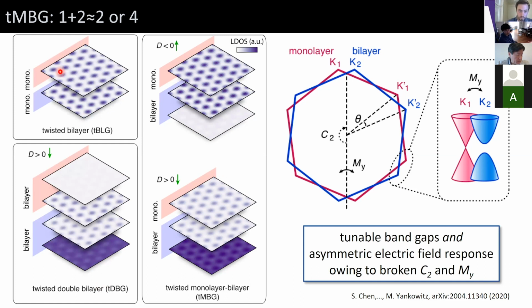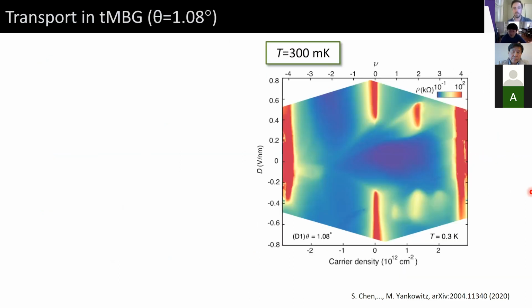So if we do this calculation for twisted bilayer graphene, it looks very much like it happens with the D negative side of twisted monolayer-bilayer graphene, but it's missing this extra layer with only a small amount of charge. Nevertheless, this layer may act as somewhat of a screening perturbation on the system. So, we can draw some rough analogy between these two. And in the same way, when we flip the sign of the electric field, the local density of states looks very similar to twisted double bilayer graphene, except now it's missing an additional layer that's only weakly charged. So from this, we might want to think that 1 + 2 is either equal to 2 or 4, but not 3. So we can do, without further ado, some experiments to see whether this actually holds water.